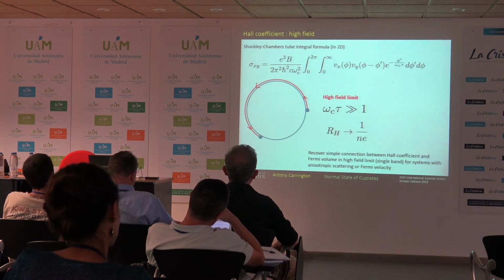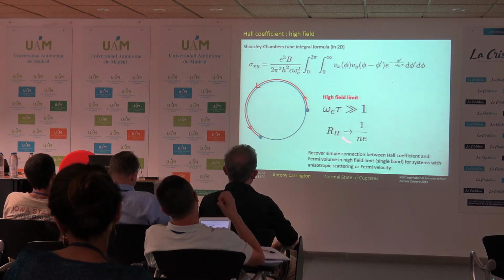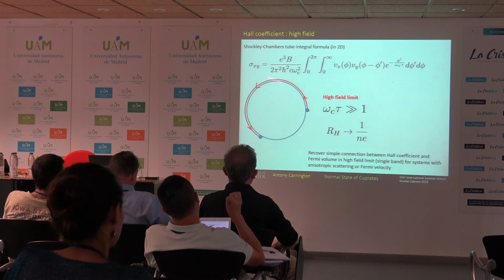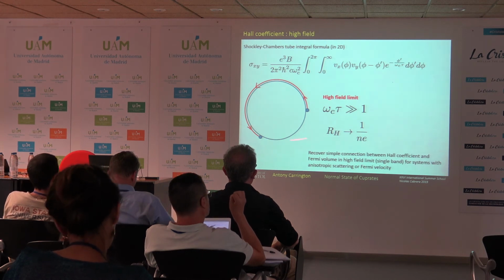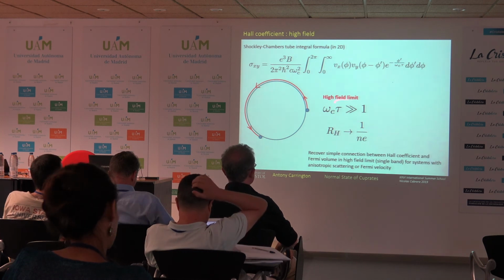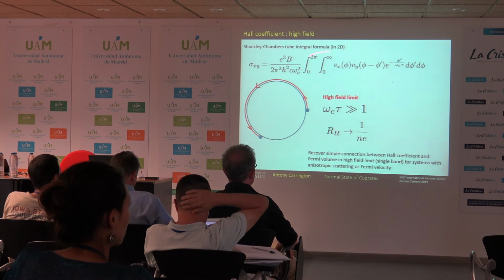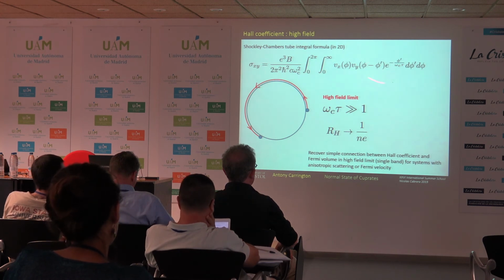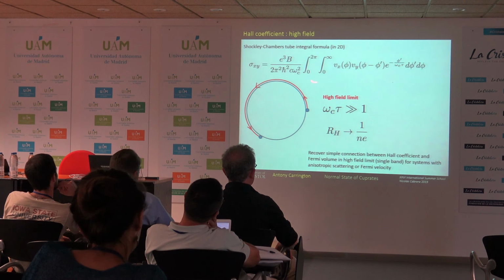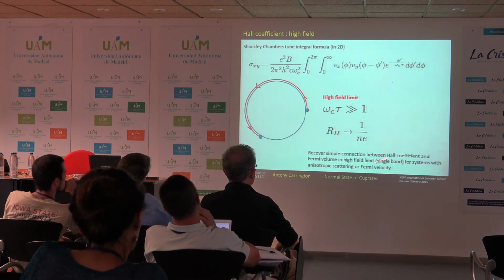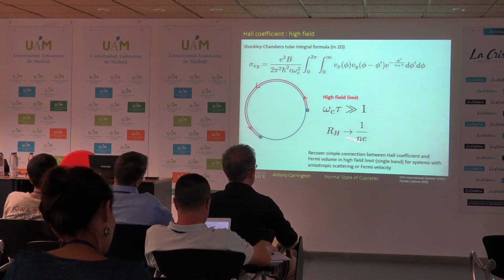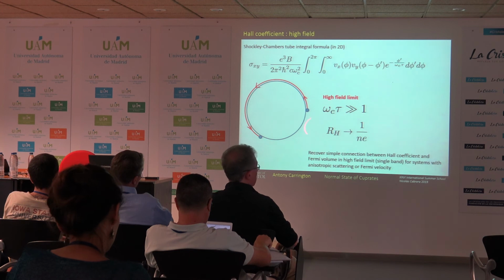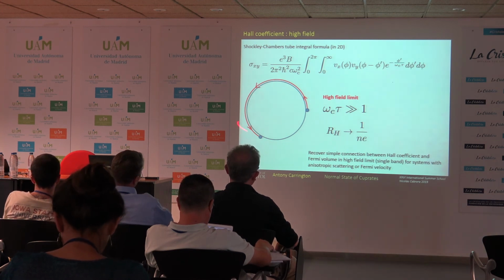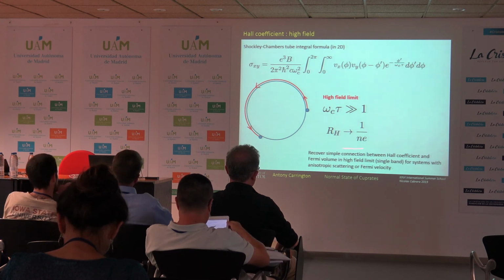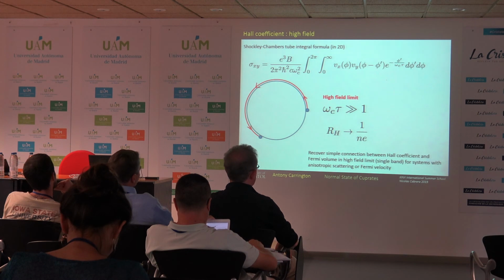Right, so let's move to what happens in high field. In high field, the quasi-particles go a long way around the Fermi surface, and in the limit that this becomes much greater than 1, then essentially you average over all the anisotropy in the scattering rate and the mean-free path, and you get some bits where it's higher and some bits where it's lower, and then because the integral goes all the way around the Fermi surface, sometimes many times, this ends up that the Hall coefficient goes back to being 1 over ne. So that means that in the high field limit, all of this business with the scattering rate anisotropy should be irrelevant, and you should go back to it equaling exactly 1 over ne.